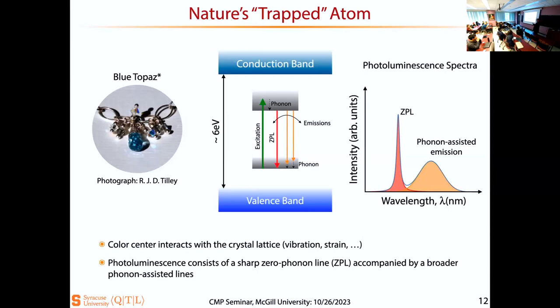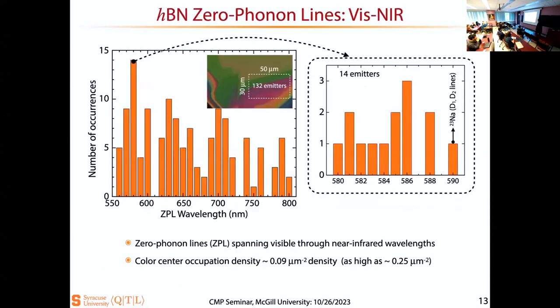Now I have spent so much time working with color centers that I don't even have to do a G2 measurement to say whether it is a single photon source or not. I just look at the alignment of the zero phonon line. If it is narrow enough, I can say that, yes, it is. But then the reviewer wants a correlation measurement to show that it actually is. But yes, this is how a typical characteristic spectrum looks.